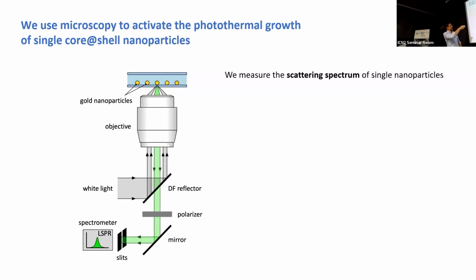So if you don't have anything, let's say you have a perfectly flat and clean microscope slide. In an ideal world, that never happens, but let's assume that you can get there. Then the light that is coming from the objective is reflected back and is never picked up by the lower NA of collection. And so what you see is completely black. Now, as soon as you have a little speckle of dust on your glass slide that scatters light in all directions, that's when you see it. And now if we put gold nanoparticles, they scatter green light very efficiently. And so we can collect the green light scattered by the gold nanoparticle, and we collect the plasmon resonance of individual nanoparticles.